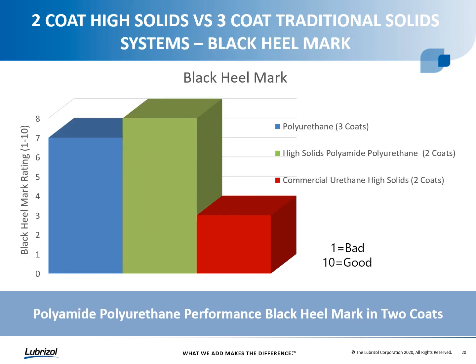Another test that we commonly run, especially for wood floor coating applications, is black heel mark or scuff mark resistance, where we intentionally strike the surface of the coating with a hockey puck, and we look at that black mark that's left on the surface and how easily it can be removed with just some mild cleaning with a cloth dampened with water. We're not really aggressively scrubbing it or using any type of cleaners, but we're seeing, can that scuff mark be removed, and then we visually assess the panel on a 10-point scale, with 10 being very good, 1 being bad.